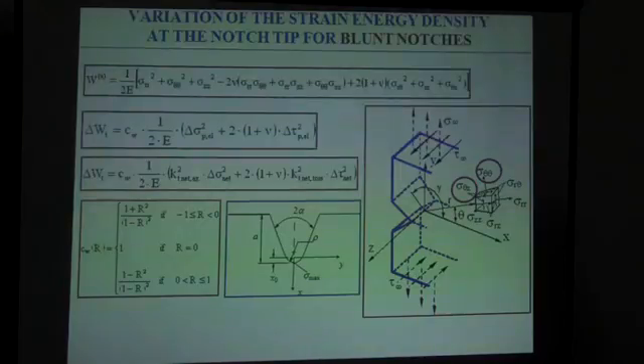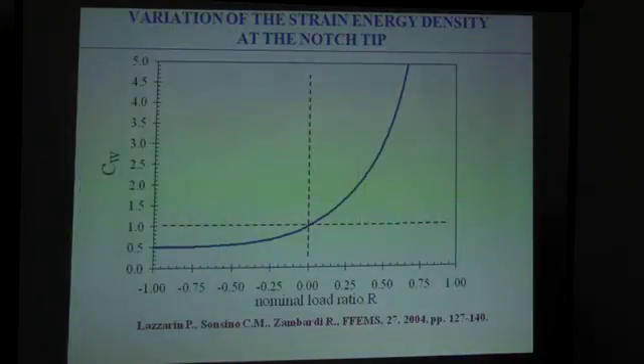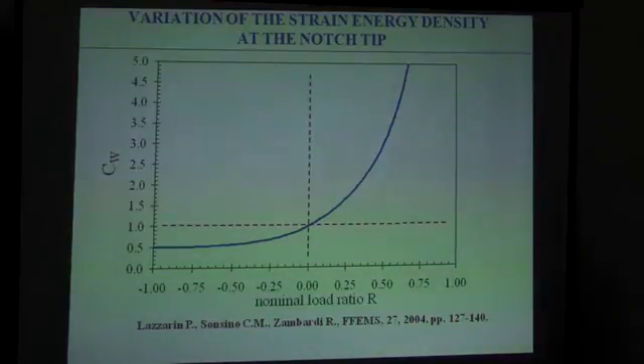Dealing with the analytical background, I don't want to bore you too much with this part, but the strain energy density has the advantage that it can be calculated taking into account the nominal load ratio with the parameter called CW, introduced by Atzori, Lazzarin and Berto in 2004. This parameter is equal to 1 when we are considering an external nominal load ratio equal to 0, and 0.5 when we are considering a nominal load ratio equal to -1.